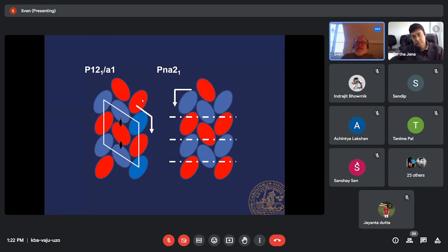So it's only second nearest neighbor interactions that differ. And of course, this makes things a lot easier for nature to use these different structures, so to speak, because the differences in energy are small. And the larger the object, the smaller the difference in energy, because next neighbor interactions happen at larger distances.